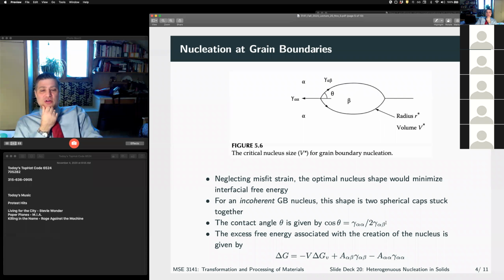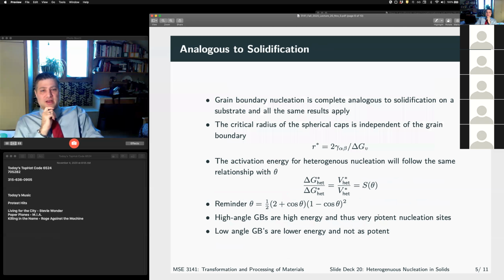right? The contact angle is going to be given by the ratio of the interfacial energies, not interfacial areas, interfacial energies, right? And then the surface energy reduction is just the difference between the amount of energy of the alpha alpha interface destroyed plus the amount of alpha beta interface added. Okay. So again, this is completely analogous to solidification, right? We have a critical radius that looks the same.